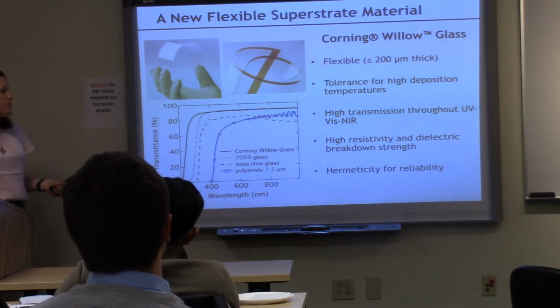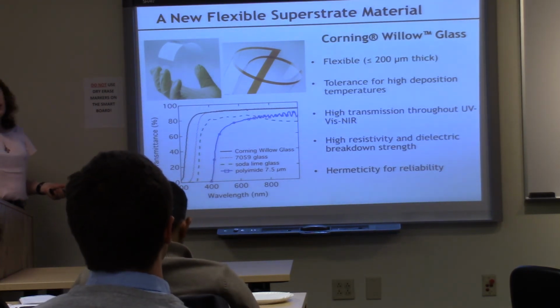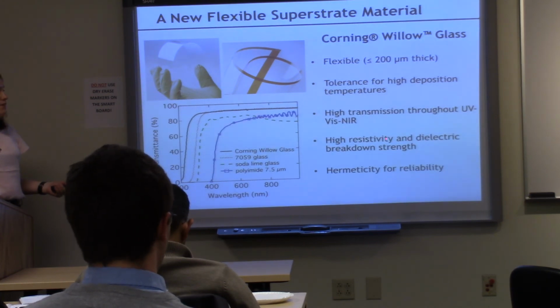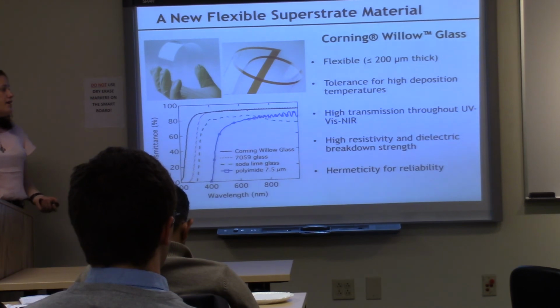transparency and optical properties. It goes up, we've taken it up to about 620 degrees for fairly long periods of time. So it has great thermal tolerance. It maintains its high transmission no matter what you do to it. And the other thing that's important is it's very resistive because it doesn't have those mobile ions in it. It has a very high dielectric breakdown strength, okay?